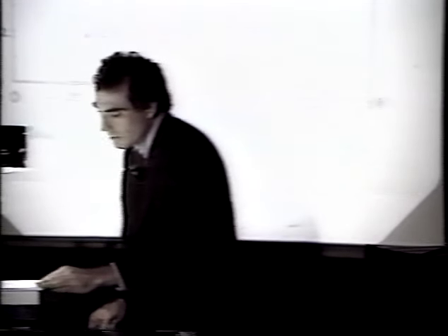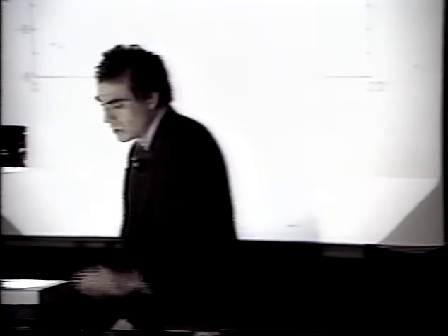As you have seen already several times tonight, substitution of europium or any other rare earth for yttrium does not change the superconducting transition temperature, and we found that for europium barium copper oxide, an onset of about 90 Kelvin. A curve of susceptibility versus temperature for this sample indicated, again, an onset at about 90 Kelvin, and we saw about 60% of the full Meissner effect.